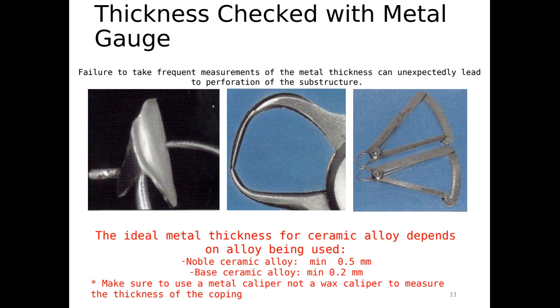Again, from time to time, we have to stop when we're doing the finishing of the metal and make sure we use a caliper to measure the thickness of the metal, okay? Make sure also to use the caliper that's used for dental alloys and not for waxing, okay? The ideal, this is crucial, ideal metal thickness for ceramic alloys depends on the alloy being used. For noble ceramic alloys, minimum it's 0.5 millimeter. For base ceramic alloys, minimum it's 0.2 millimeters.